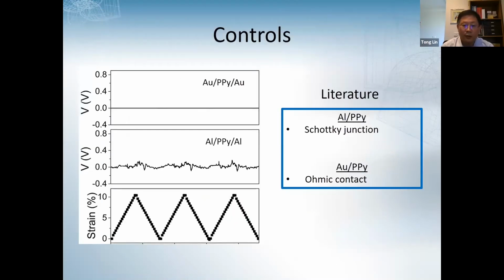We also tested control devices. If we use gold as the electrode on both sides, we cannot get any signal from the device. If we use aluminum as the electrode on both sides, we get a complicated output like this, which includes both positive and negative signals, but the output is very small. In the literature, conducting polymer PPy forms a Schottky junction with aluminum, but forms an ohmic contact with gold. Therefore, our device should contain a single Schottky junction.